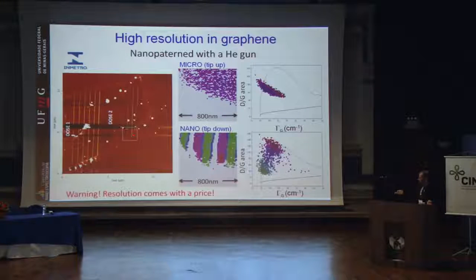But then if you land the nanotip here and you scan with the tip, you see that this image becomes like this, okay? So here the material has been completely sputtered. Here the material has been destroyed a little bit, and here the material is more pristine. And then you see that with the resolution given by nano-Raman, you don't see a uniform distribution, but the distribution of defects is much higher. Some regions have very low density of defects, and some regions have very high density of defects.